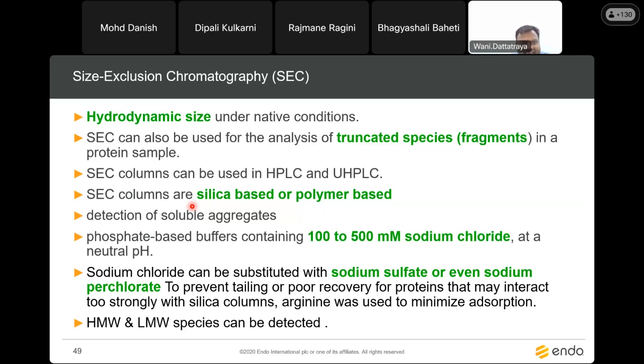Generally, soluble aggregates are obtained by using size exclusion chromatography. Generally, we use a phosphate based buffer containing 100 to 500 millimolar sodium chloride at neutral pH. By using sodium chloride, sometimes you will not get the proper peak shape, or you have tailing or improper recovery of some fragmented peaks. So sodium chloride is replaced with sodium sulfate or sodium perchlorate. That will give you a better chromatographic peak shape. High molecular weight or low molecular weight species can be detected by using this technique. High molecular weight species are nothing but aggregates, and low molecular weight species are your truncated or degraded peptides that you can get with this size exclusion chromatography.